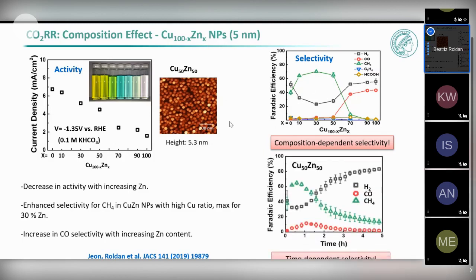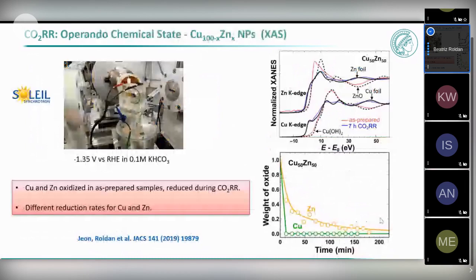But even more, if you look as a function of time, here you can see the copper zinc nanoparticles. Initially, you are making methane, which is very interesting, but after 1 hour, we see a change in the selectivity. Here we see that we are making hydrogen, and in this case, the selectivity is changing after the first 2 hours or so. So what happens to our catalyst? It's not enough to know what happens to the pre-catalyst that we are making. We need to understand what caused this change in the selectivity. And to see that, we can do it under reaction conditions.